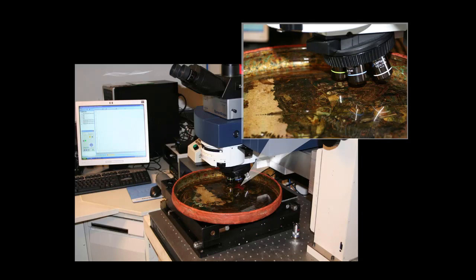Look at the object I'm focusing on there. That is a Renaissance paten, a shallow bowl used during the Eucharist from Germany. It's what we call reverse painted glass. The painting is on the outside, on the underside of the glass bowl, and it's sealed with a layer of wax. The painting materials are protected by the glass and by the opaque wax at the back. There's no way you can get to it. You cannot analyze it with X-ray fluorescence spectroscopy because you just get the signal from the glass. With Raman, we go through the glass, we recover the signal of the materials, and we can analyze it. So Raman is quite a valuable technique.